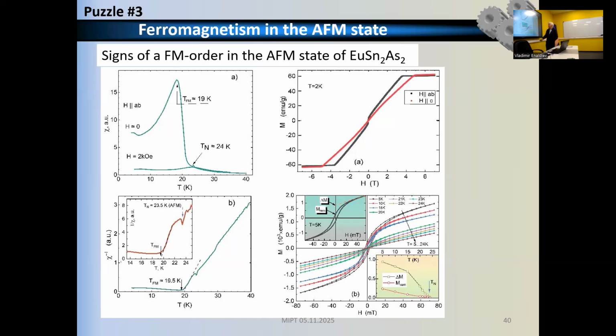And all characteristics of this hysteresis, like the magnitude and the width, drop down to zero at the temperature of antiferromagnetic ordering. So that already suggests that this ferromagnetism is just born by the antiferromagnetic ordering. So the two phenomena are very closely related. These signatures are also enormously large here when we take measurements of the susceptibility.